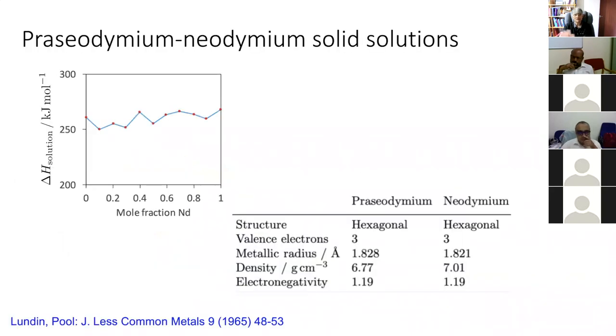Okay, now, we have mentioned repeatedly that we are assuming that there is no enthalpy of mixing, or the enthalpy of mixing is close to zero. And there is only one solid solution that I discovered after talking to Nirupam Chakrabarty, which has a zero enthalpy of mixing. And that's the praseodymium and neodymium alloy system.